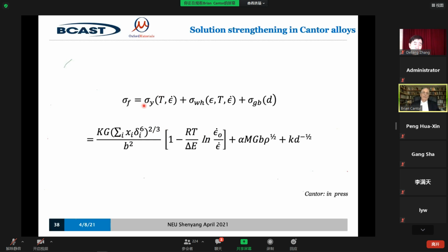For a while, people thought it was the Peierls stress that was higher in these multi-component alloys, but it's not the Peierls stress. It is that difficulty of moving the dislocation through the strained lattice. And this is quite hard to get a theory of, but this is the best theory we have at present. And it depends upon these deltas. These deltas are the sizes of the individual atoms.